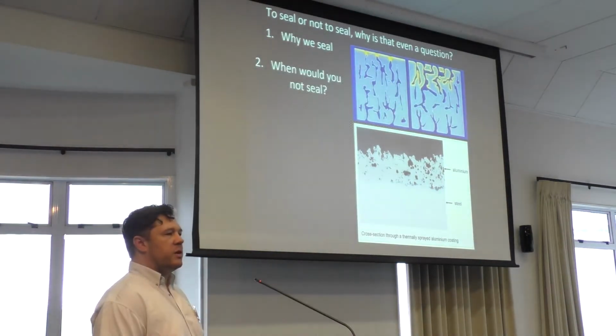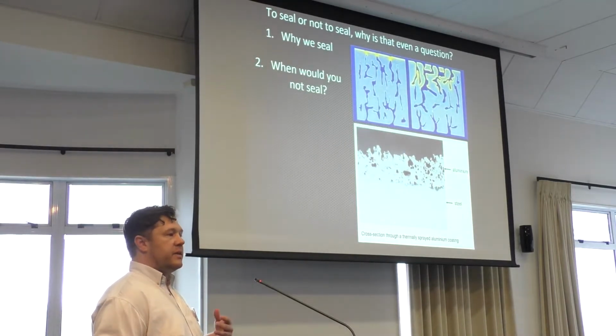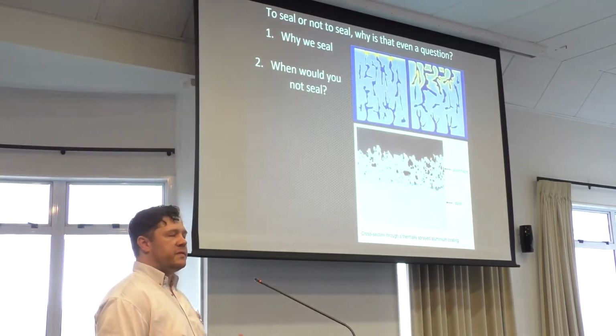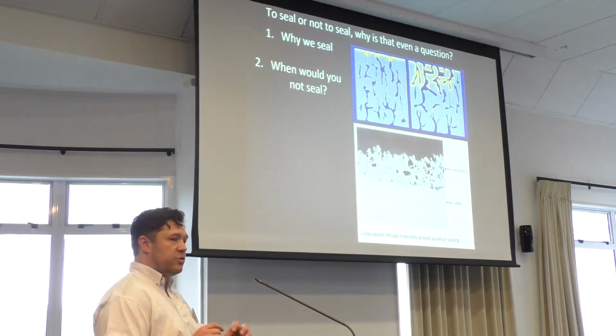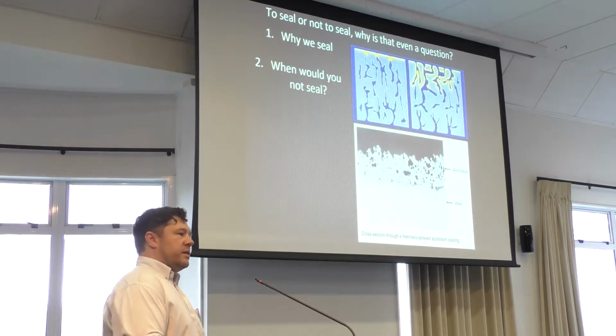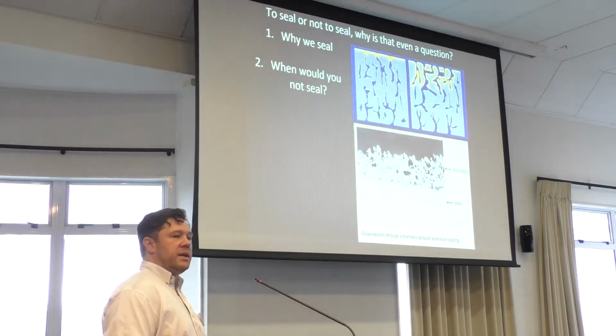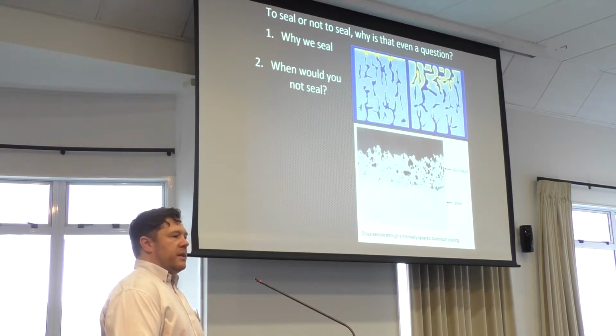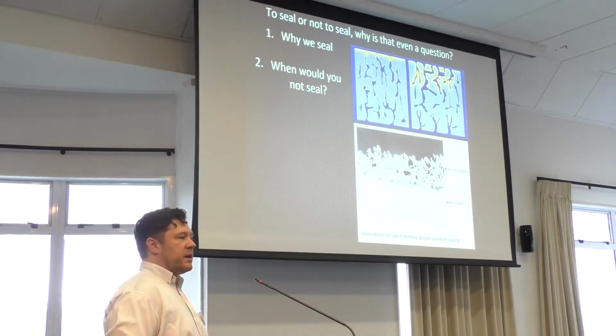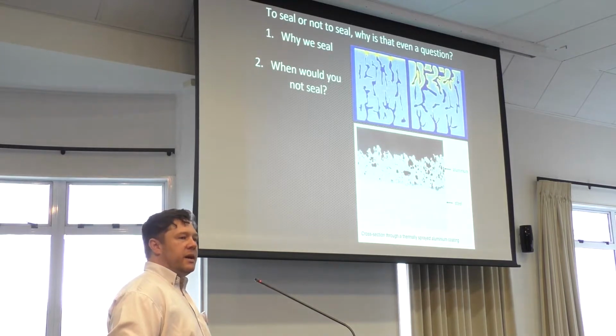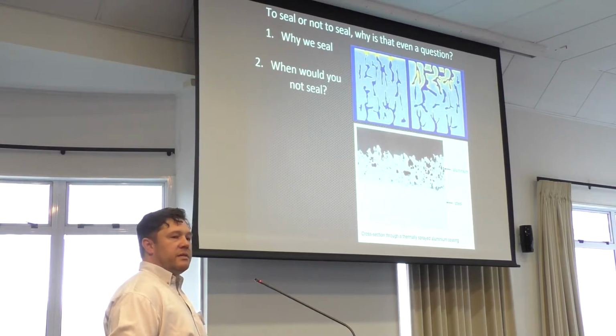When would you not seal? So if we're going to immersed situations, we've learned over trial and error that if we apply aluminium and then put a sealer over top of it that's not a very soft sealer, we can run into troubles with blistering on the coating and accelerated corrosion in the blistered areas. So to avoid that, we either put a little bit more aluminium on and omit the sealer completely, or we seal with something soft like silicone, and silicone really has been the only one that's proven to work. Now that lets any hydrogen gas or anything that's building up inside the coating out, because the water always finds its way into the pores. The salt water creates hydrogen when it reacts with the aluminium, and that'll pop the bubbles off and cause the blisters. If we're using silicone sealer, it lets the bubbles of hydrogen out without blistering, so it seems to be a good way to go about it.